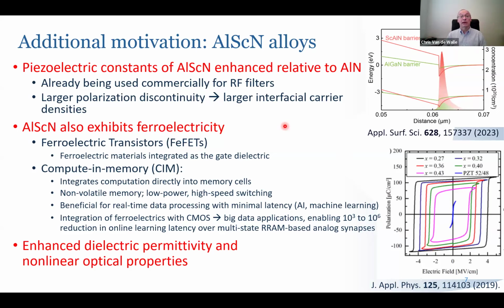But in 2019, Simon Fichtner in Kiel in Germany demonstrated that you can actually switch the polarization of an aluminum scandium nitride alloy. These are the loops that he observed for various concentrations of scandium in the alloy, and he measured large values of polarization. So this is extremely exciting because you can now envision all kinds of applications, ferroelectric transistors in which the ferroelectric is integrated as a gate dielectric, but also, of course, in the context of ferroelectrics, memory type devices where you can integrate computation with memory cells.